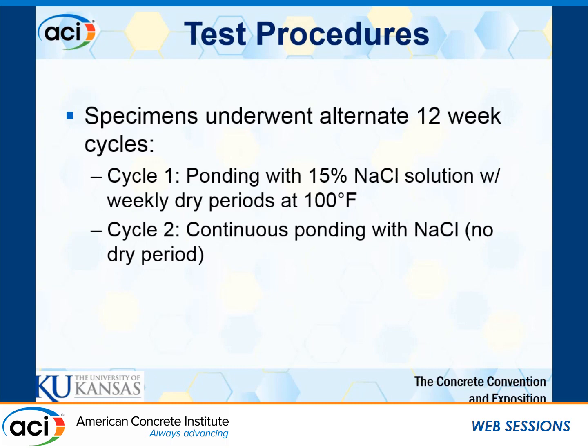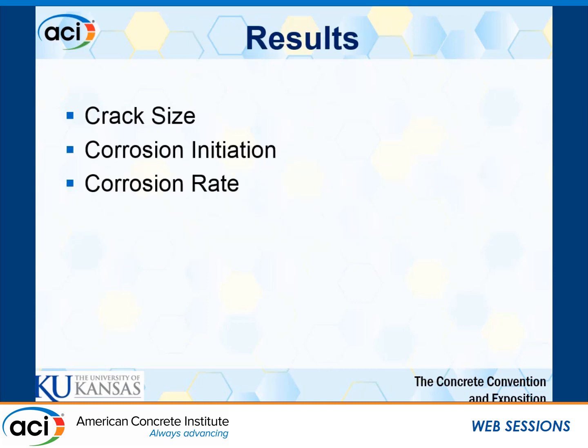Our test for corrosion behavior involves 2 cycles, 12 weeks each, the first of which is wetting and drying. So they'll be ponded with our salt solution. We take our electrical readings. Those are then vacuumed and dried off under heat at 100 degrees Fahrenheit. And then the other 12-week cycle is just composed of continuous ponding.